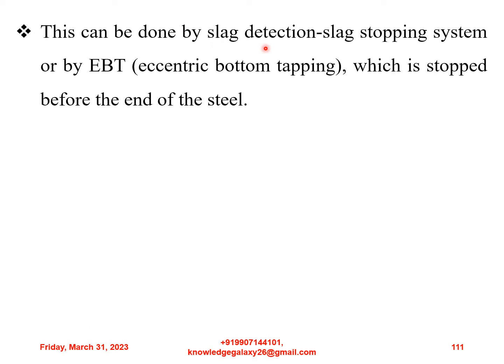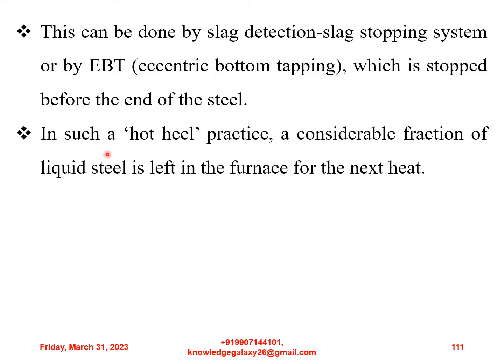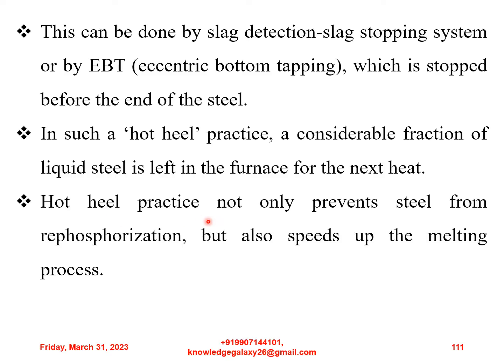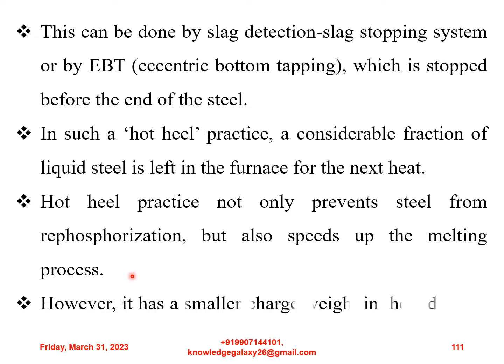This can be done by slag detection, slag stopping system or by EBT, that is eccentric bottom tapping, which is stopped before the end of the steel. In such a hot heel practice, a considerable fraction of liquid steel is left in the furnace for the next heat. Hot heel practice not only prevents steel from rephosphorization but also speeds up the melting process. However, it has a smaller charge weight in the ladle as a drawback.